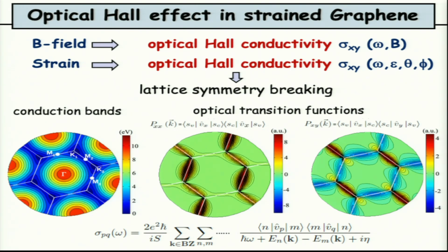And where does it come from? In fact, if you strain graphene, you will not get anymore a perfectly hexagonal Brillouin zone. So the K and K prime points are no more equivalent in this case. And also the M1, M2, and M3 points, which are at the center of the segments of the Brillouin zone, are also completely different due to the strain and depending, of course, on the direction of the strain.